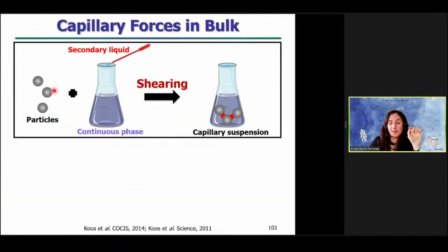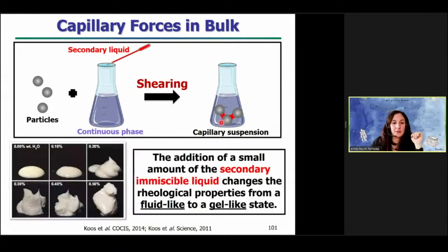Liquid will wet the surface of the particles, and just by shearing, when the particles enter into contact, they will form capillary bridges and form some capillary suspension. So here you can see on this picture an example of micron-sized particles dispersed in a solvent. And when they add a little bit of water, the water being immiscible with the continuous phase of the solvent, you have the formation of the capillary bridges between the particles, and you can see the drastic change of the rheological property from a fluid-like to a gel-like state. So our idea was to use these capillary forces in bulk to bind permanently the nanoparticles.